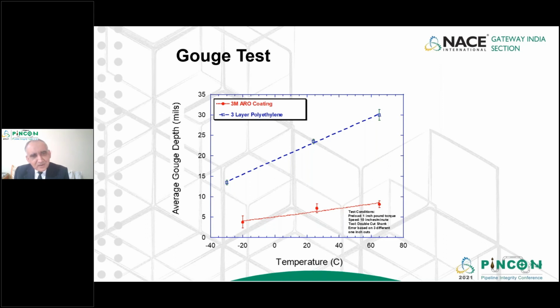So this is generally not noticed by anyone. The reality is that the pipeline is constructed with a heavy gouging action unnoticed, and those are the potential crisis situations: in long-term service performance, the portion which is suffering heavy gouge will start higher-level corrosion. So this is something now coming into the specification that at a certain frequency, the coated pipes need to be tested for gouge. And that's the responsibility of the applicator, how to organize that test. So it's very important for long-term performance.